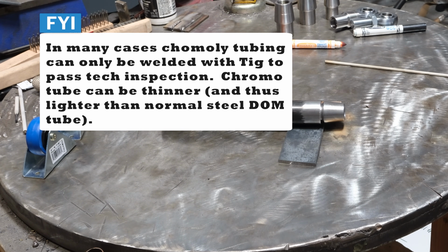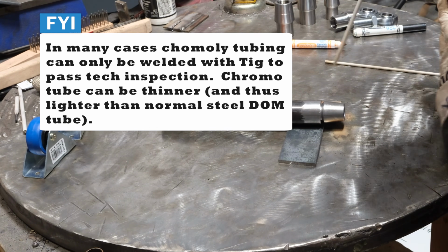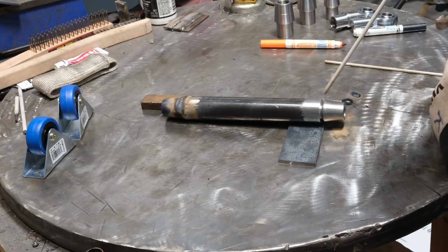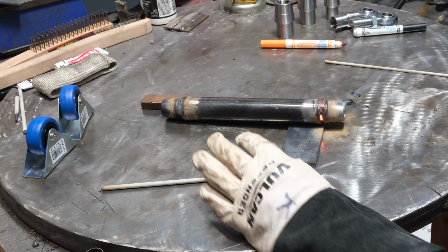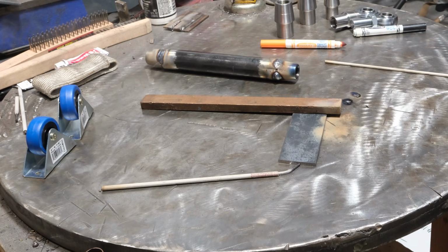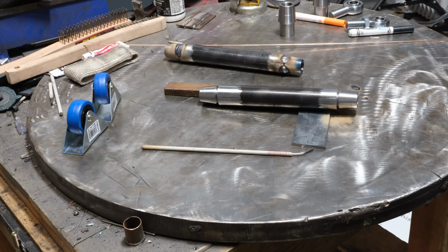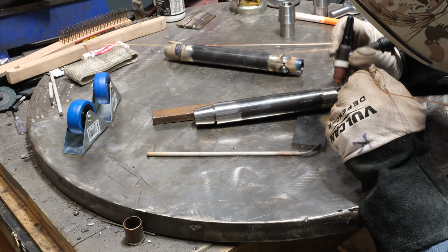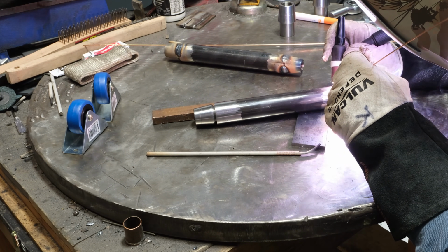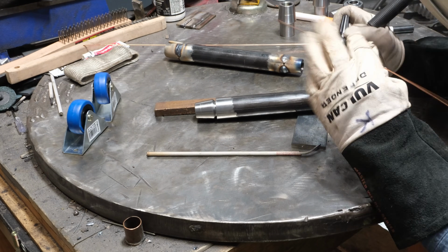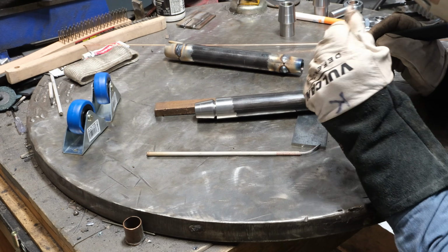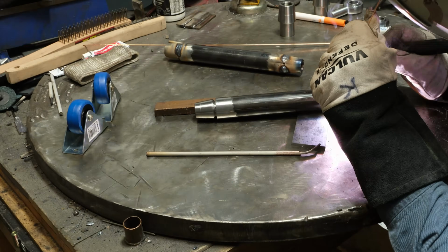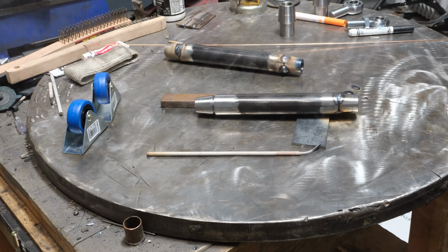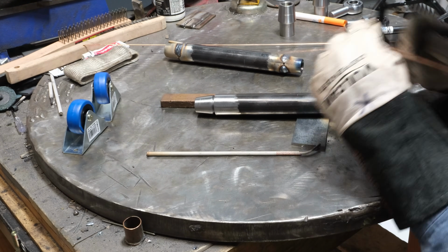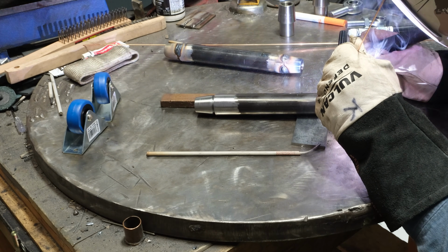Now, for you guys that do stuff like I do, where you build stuff and then go out in the woods and destroy it, obviously you can do anything you want. And it's not that stick is incapable of welding, say, a cage or a tube like this properly. It definitely is, and definitely will make a strong weld. The issue is that at some point you have to draw the line. If you allow stick welding in, then you're going to get a lot of bubbas, no offense to anyone, that are going to basically weld a cage together with 6010 and likely have a failure due to, one, the weld being so much weaker than the base material, and two, weld defects being far more prevalent with stick than probably MIG because of how difficult it is to weld something that's small bore, like 1.5 inch, 1.75 inch tube.